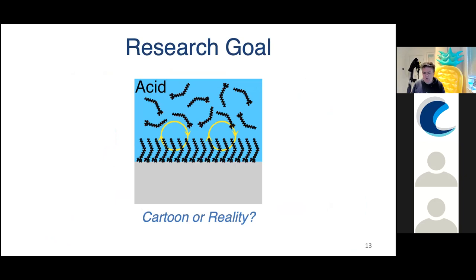So what's our research goal? We're not really trying to find new corrosion inhibitors in our research. We're trying to understand how current corrosion inhibitors work in a lot more detail, so we can move away from this empirical selection process. To summarize what we're doing, this is a cartoon I've shown before, where we're forming this monolayer at the surface. But is this just a cartoon, or is it anywhere close to reality? For example, a key point is, are the molecules really adsorbing on a clean, salt-free and oxide-free surface under acidic conditions? Or, as some literature suggests, are they adsorbed on top of a thin layer of oxides or salts on the surface? That's the sort of thing we want to know, because that would be really useful input for modelling, and to be able to select inhibitors for specific situations.